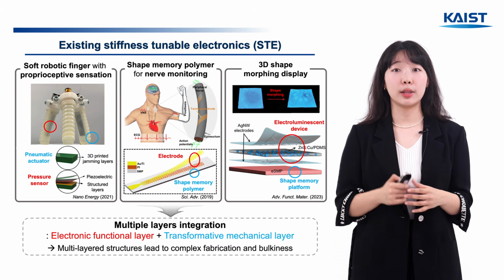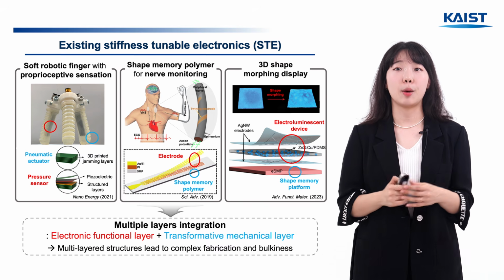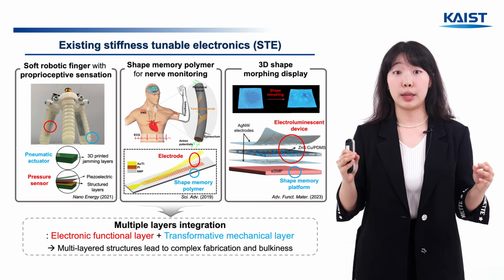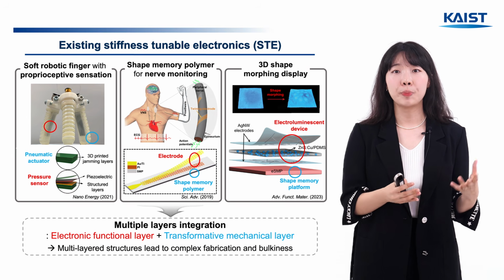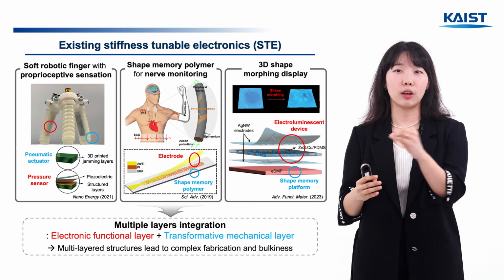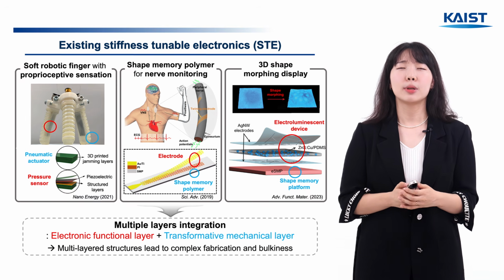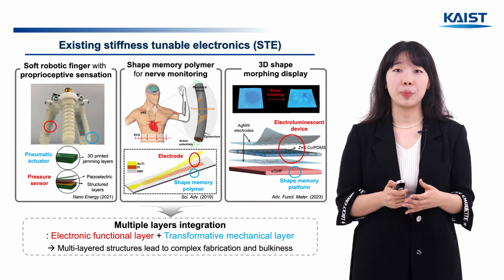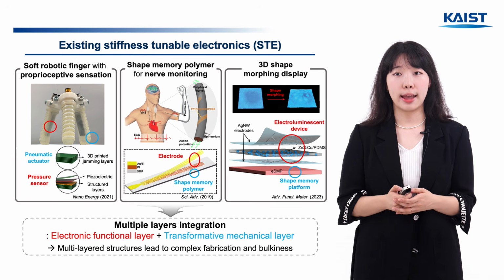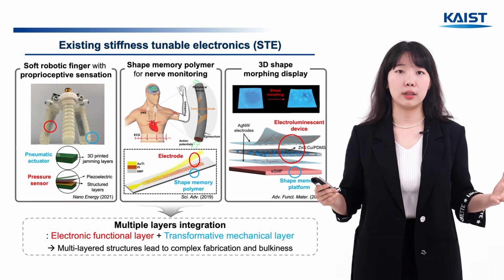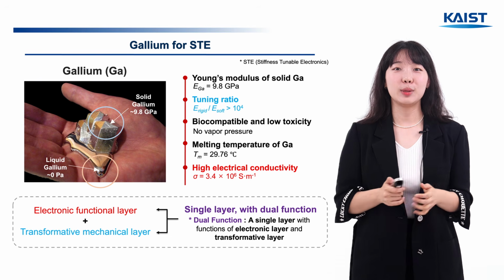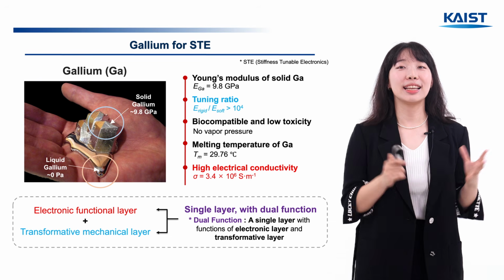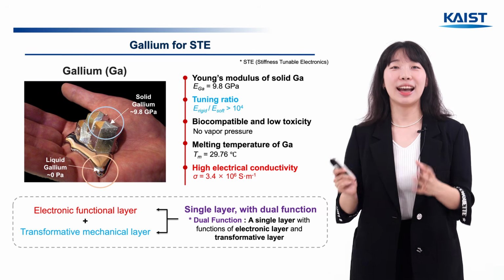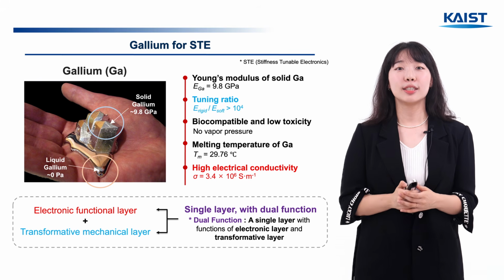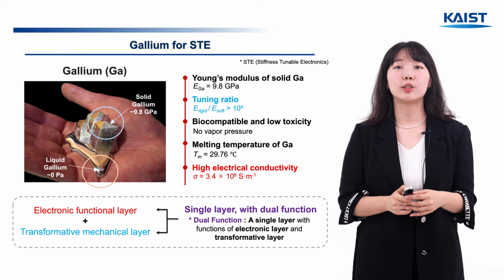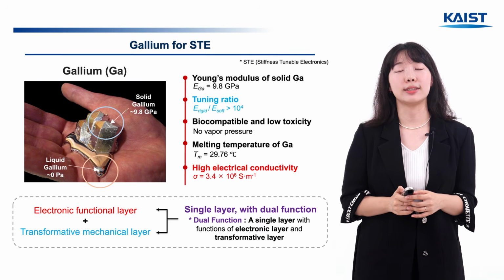Conventional stiffness-tunable electronics were made by building a mechanical structure layer by using a stiffness-tunable material, and then stacking an electrical functional layer on top. But this kind of multi-layer stacking made the process complicated and the final device very bulky. Gallium, on the other hand, has both high stiffness tuning ratio and high electrical conductivity. So gallium has the potential to perform both functions with a single material.